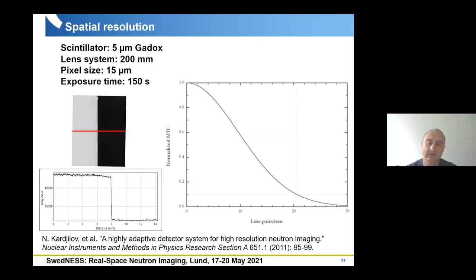You see here, this is one step edge, or one edge, which we visualized with neutrons. This was a thin foil of gadolinium which we had in the beam. And we measured this with a pixel size of 15 micrometers. So this is the signal which we obtained just by measuring the intensity. And you see that it's quite a sharp edge, but nevertheless, there is a small broadening here. And after taking the MTF, or the modulation transfer function, you see that with the increase of the line pairs per millimeter, we have a reduced contrast at 10%. We have 20 line pairs per millimeter, which corresponds to 25 micrometers.